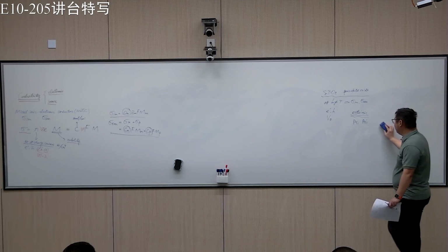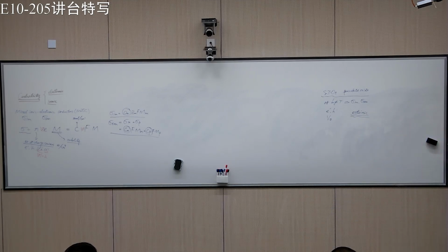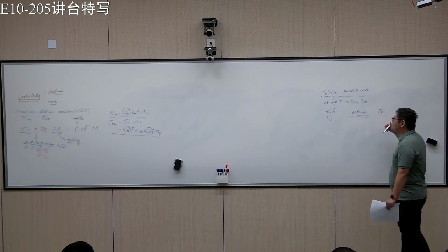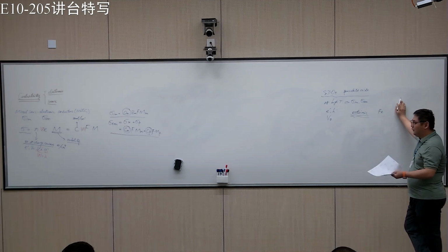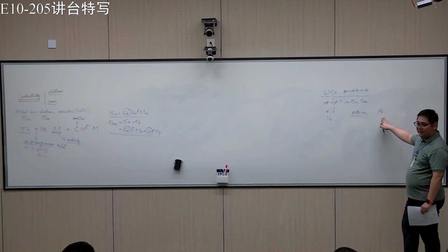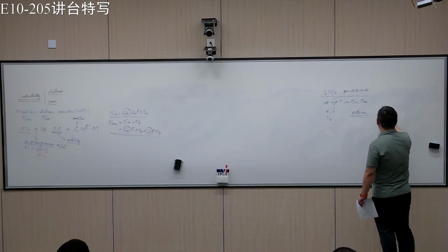If you buy strontium titanate as a single crystal, it's very likely already doped with impurities. Most commonly you have iron, aluminum, or magnesium. When you make these crystals, some impurity goes into the structure. Assume it's iron, which usually takes up the titanium site.